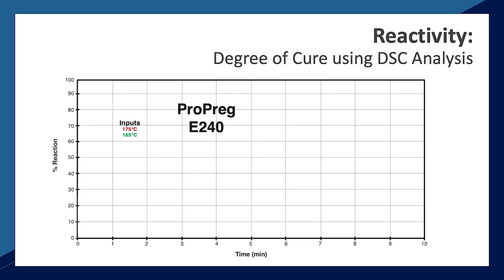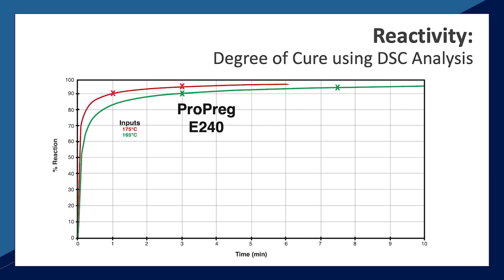This graph shows the ProPreg E240 cure time at a temperature of 165 C achieves a degree of cure above 90% in only 3 minutes, and at 7.5 minutes, the degree of cure is above 95%, which is typically considered fully cured. When increasing the cure temperature to 175 C, the E240 reaches a 90% cure in 1 minute and reaches a 95% cure in 3 minutes.